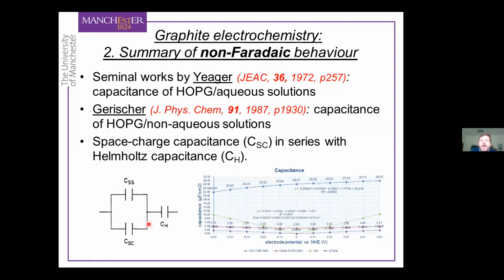And Gerischer basically used this model, equivalent circuit model, to rationalize the capacitance of graphite. So if there's only one thing you learn about this lecture, I hope the one thing that you'll take away is that graphite is in fact a semi-metal. So that means it has a low density of states near the Fermi level.